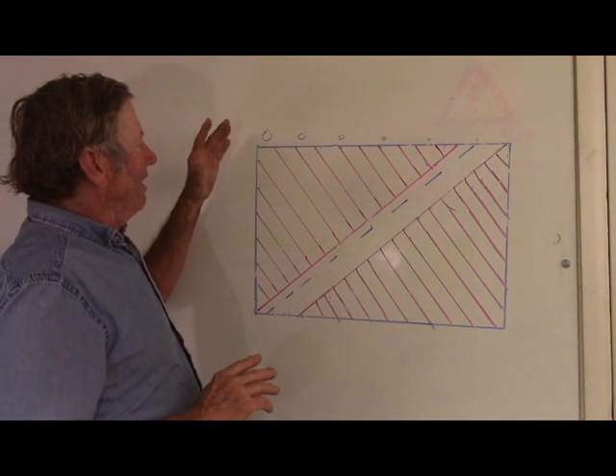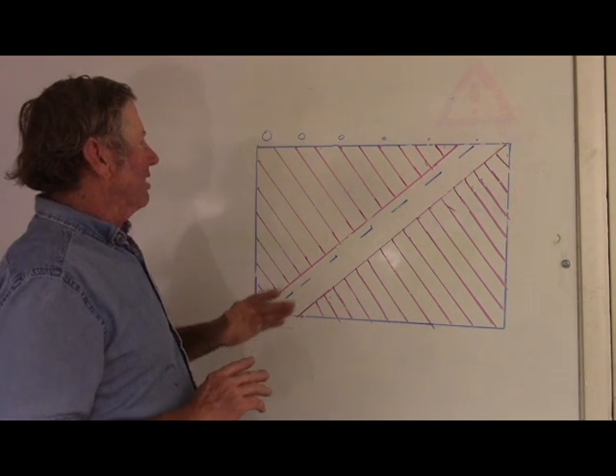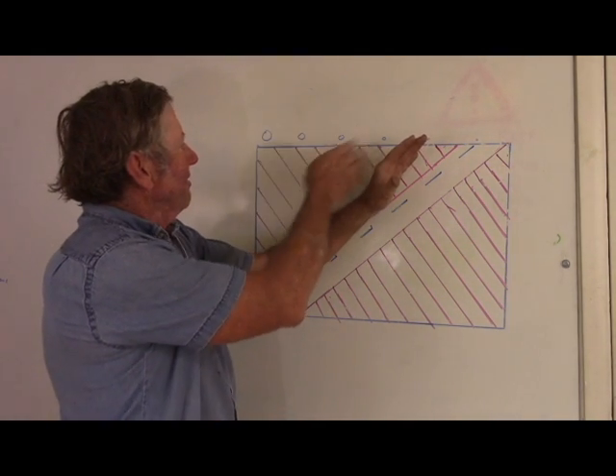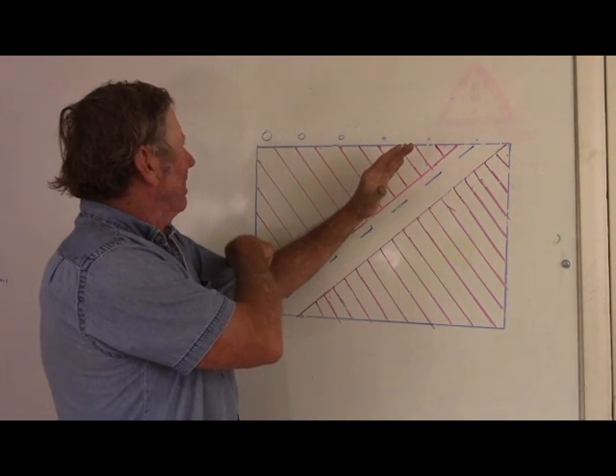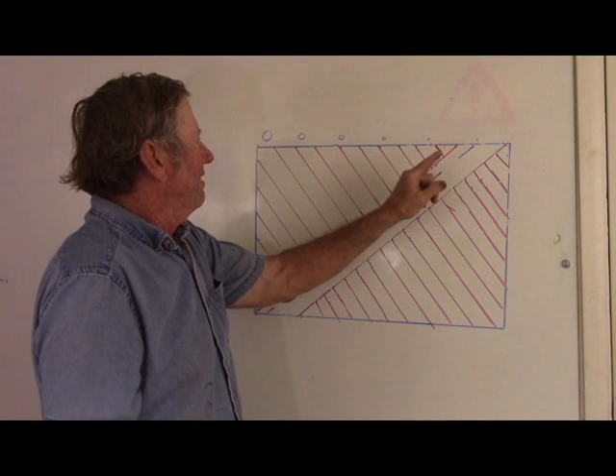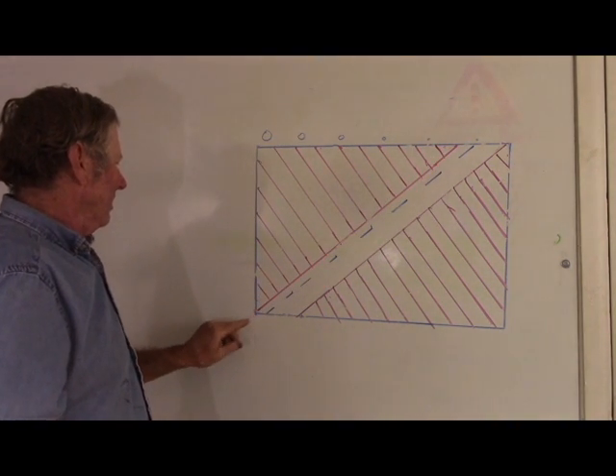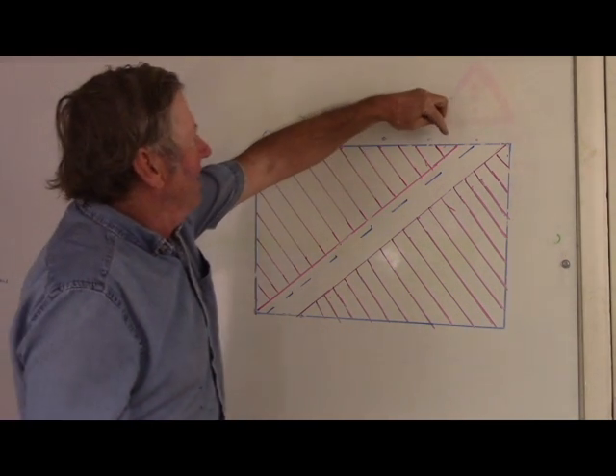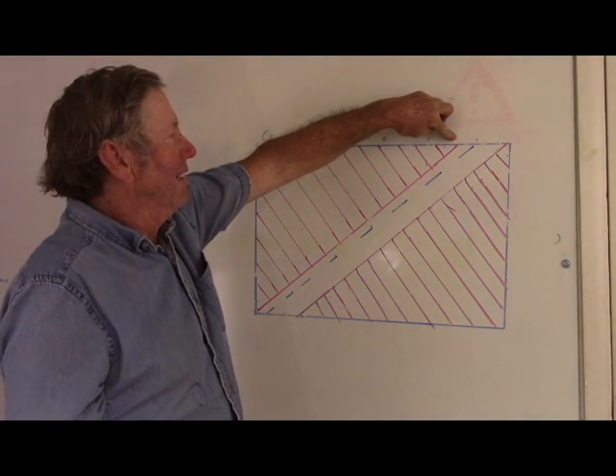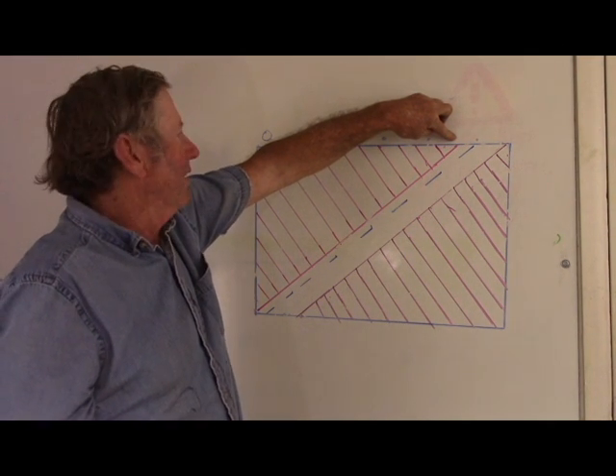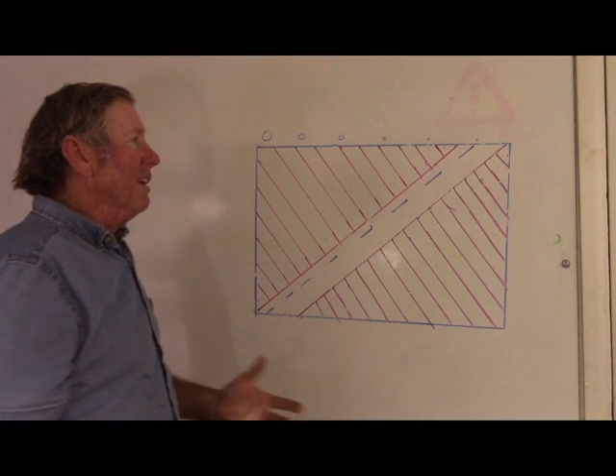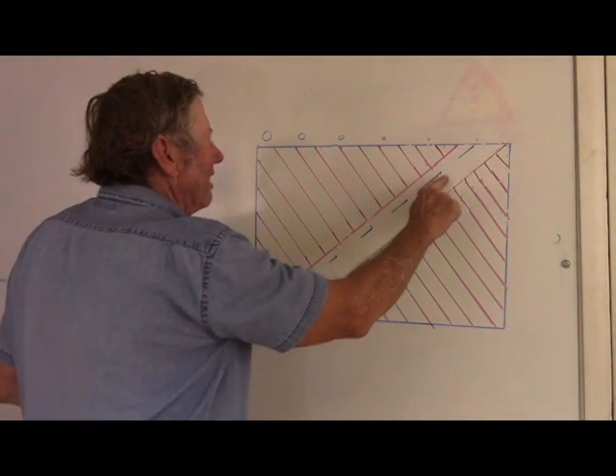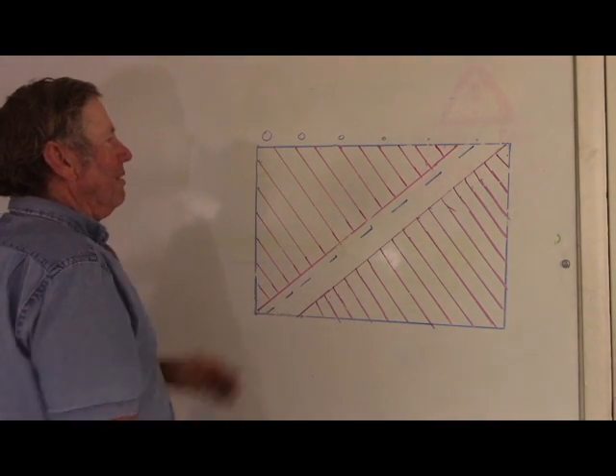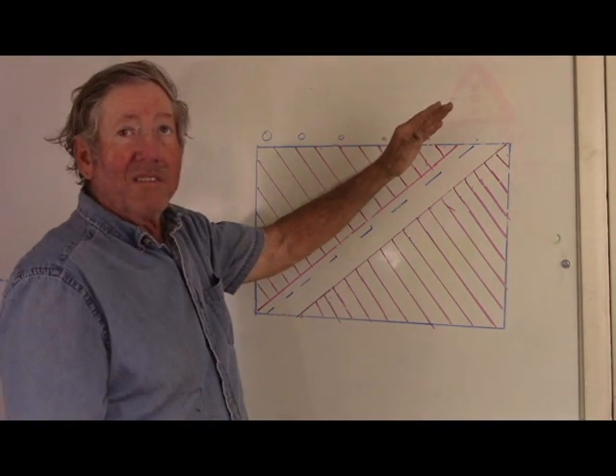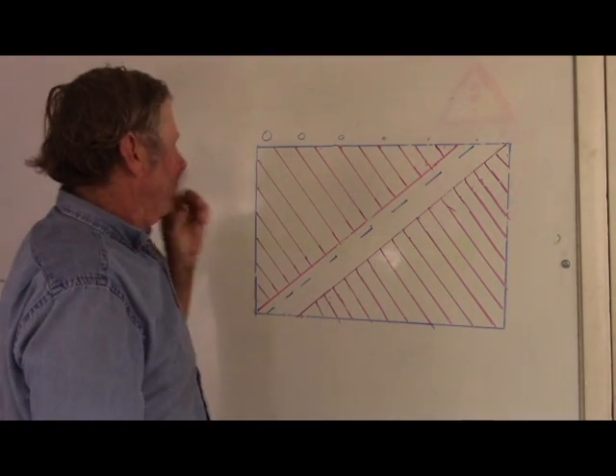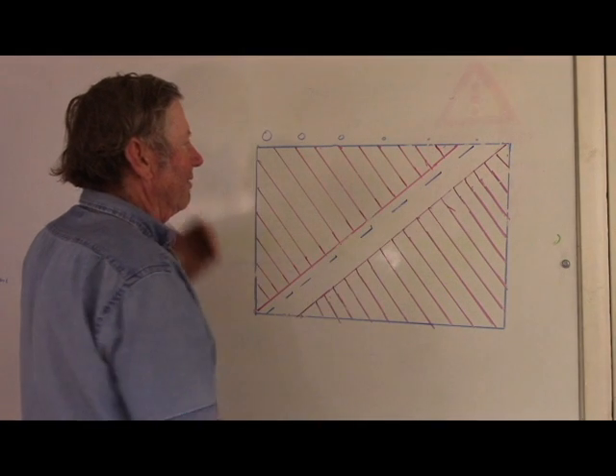Now, if you have a simple gravity extraction, it's going to get some of this gold here. Okay? It's going to get more of the big gold, less of the small gold. A decent gravity extraction, I'm estimating this line here, almost 100% of the coarser gold, and then it reaches a point here where you're just not recovering anything anymore. It's just floating off on you. If you work really hard and get a better system, you may get to this dashed line here. But everything below this line is going to be lost. And as you can see, that's a lot of gold. This is roughly a 50% line here.